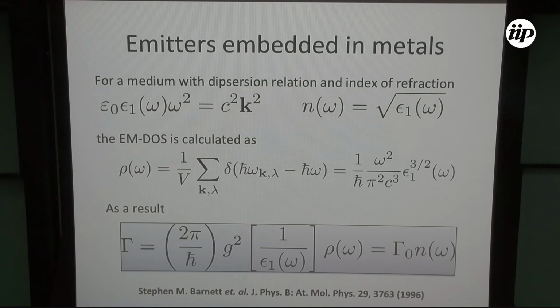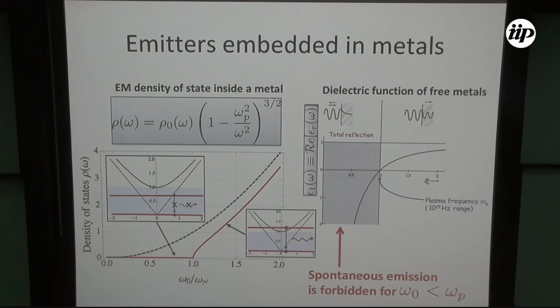So, one final slide of calculations. For this dispersion relation, and knowing that the index of refraction is the square root of the real part of the dielectric function, we can calculate the density of states to obtain this result here. It is the real part to the 3/2 power. Now we plug this back into the calculation of gamma, and there's a nice result, which is simply that the spontaneous emission rate inside the material, the metal, is just the result of the vacuum multiplied by the index of refraction. So what does it mean?